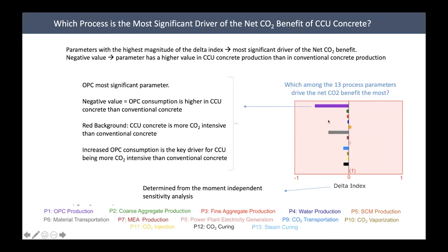And as you can see, the background is red. So that means because OPC consumption is higher in CCU concrete when compared to conventional concrete, CCU concrete tends to be more burdensome in terms of climate impact. So this is how we interpret the graph. If it is in the negative direction, the parameter is higher for CCU concrete. If the bar was in the positive direction, that means it's higher for conventional concrete.